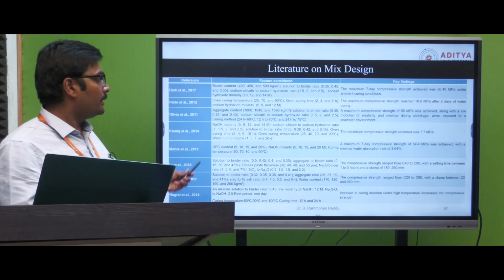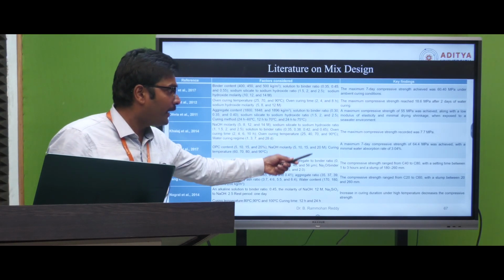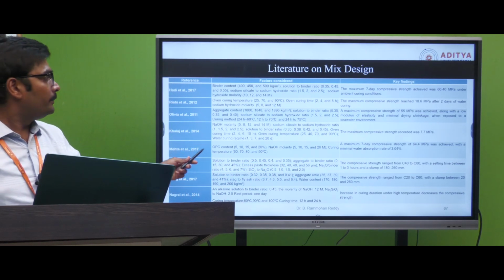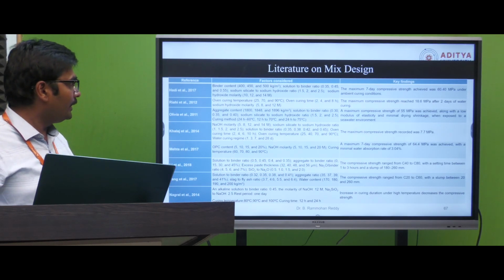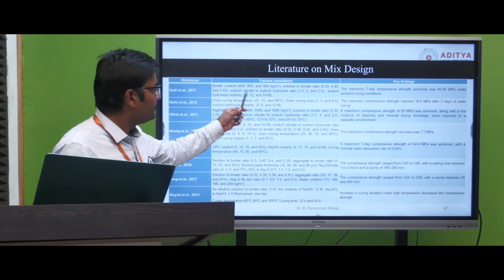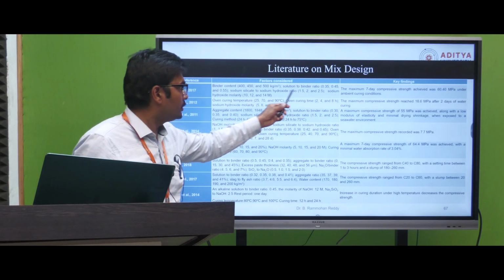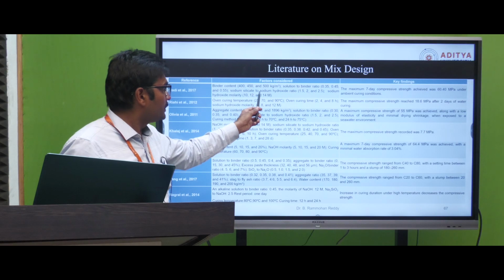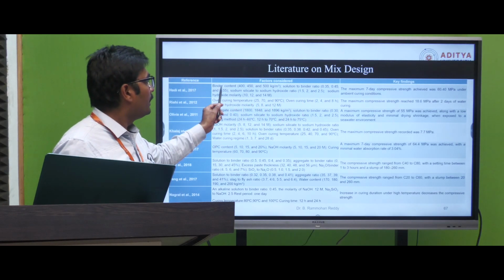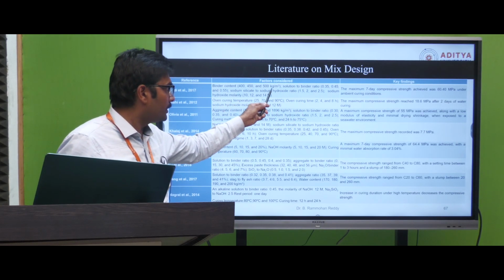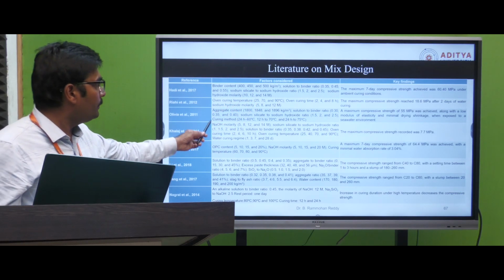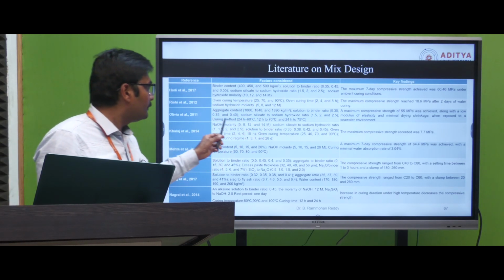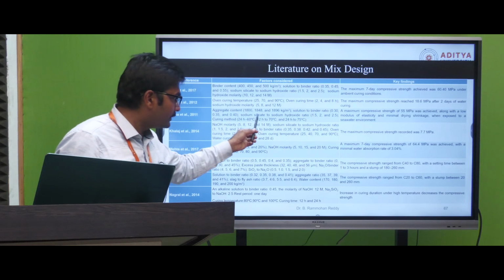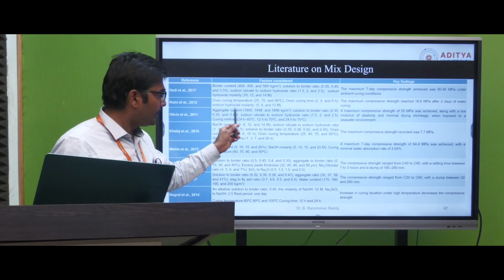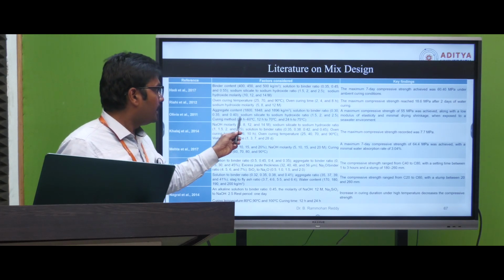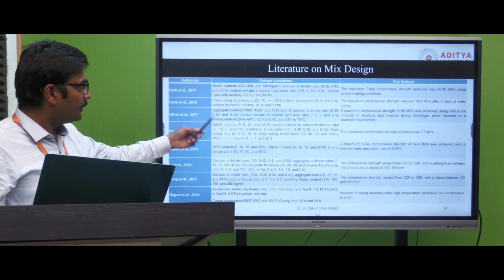In the literature, these are the various mix proportion factors considered by various authors in different years. You can see different molarities, solution to binder ratios, sodium silicate to sodium hydroxide ratios, the binder content, the quantity of binder we are choosing in kg per meter cube, the type of curing, the aggregate density and quantity, heat curing or conventional curing.